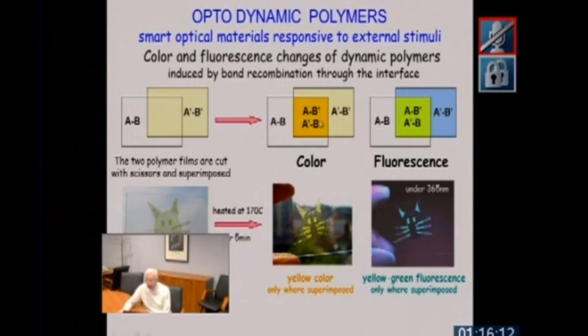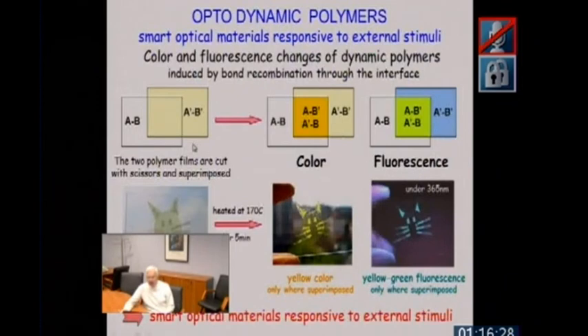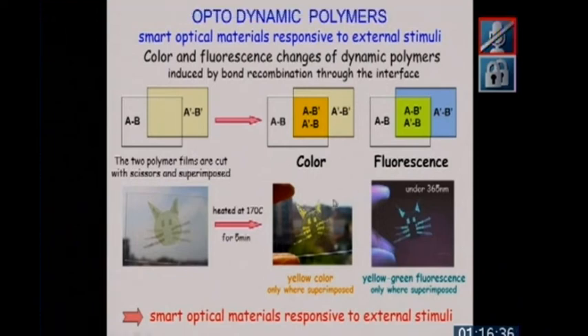It also shows that if you have such a superposition of films, you can perhaps write with a heating laser at the interface. And if you superimpose a stack of those films, you can even write in 3 dimensions in principle. So you have optical material which is responsive to external stimuli, in this case, simply temperature. And you can then make these drawings.